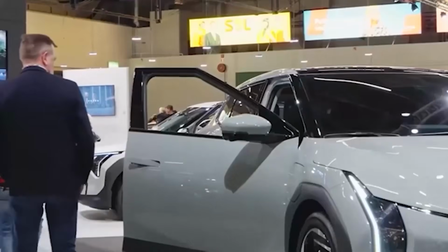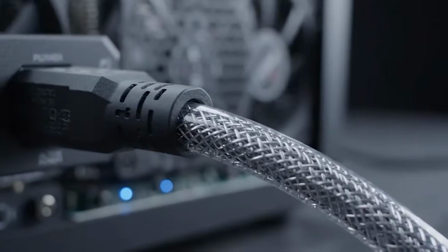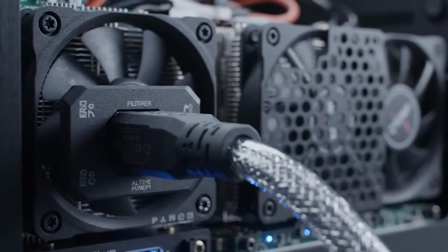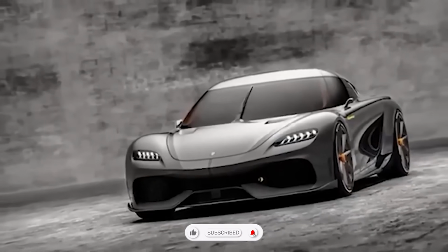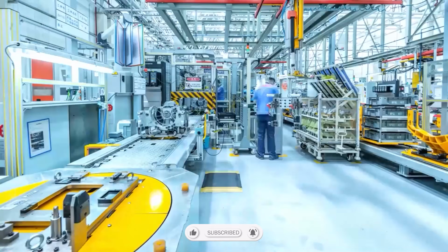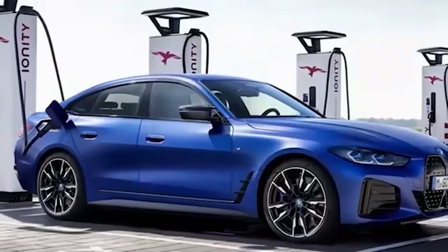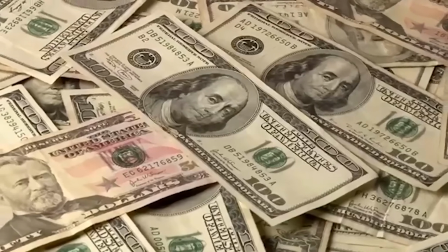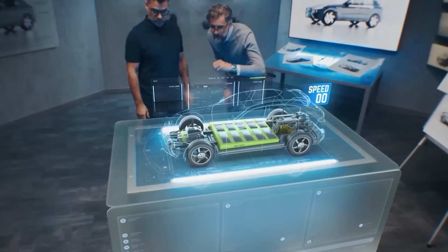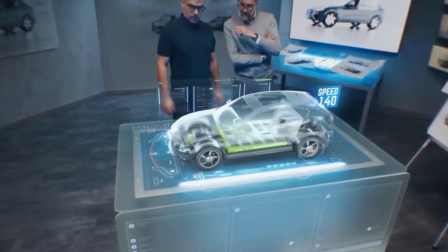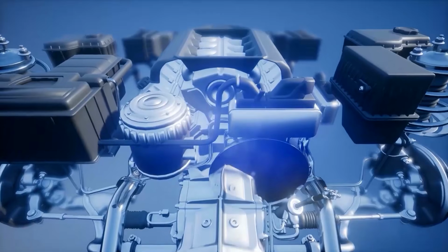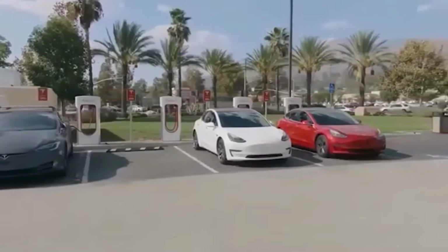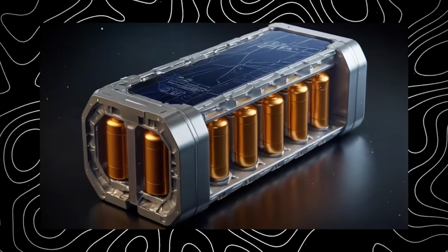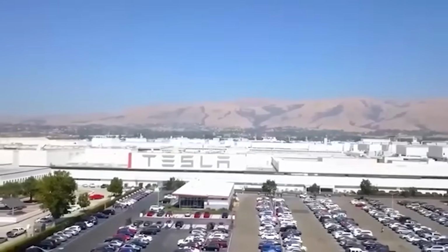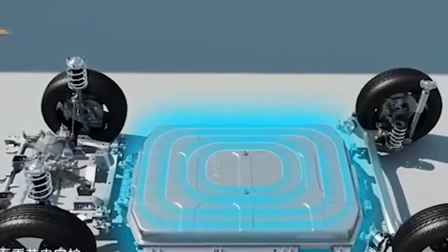Then there is the cold weather problem. The American Automobile Association tested 5 EVs at 20 degrees Fahrenheit with the cabin heater running and found an average range loss of 41%. The worst-performing vehicle lost nearly half of its usable range. At freezing temperatures, lithium ions move so sluggishly that they begin plating onto the anode surface as metallic lithium instead of slotting between the graphite layers. That plating can grow into sharp, crystalline spikes, called dendrites, which can pierce the separator and short-circuit the cell.